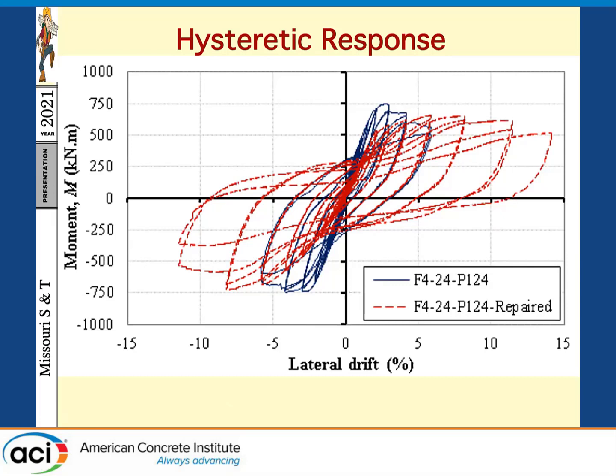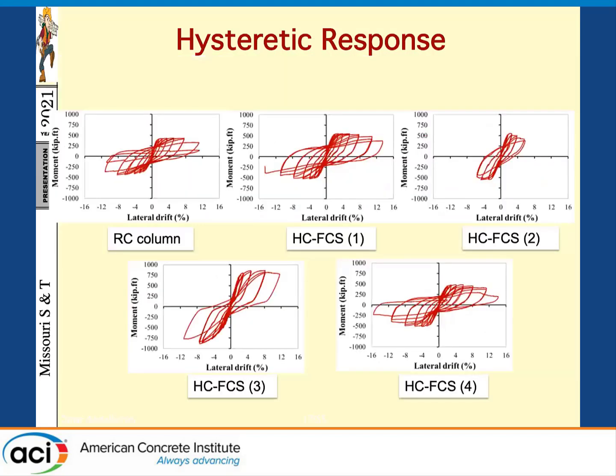One of the shortcomings of the repair was the initial stiffness. So the initial stiffness, if you look here for the blue one, is much higher compared to the red one. This was mainly due to the micro cracks that occurred in the concrete, and potentially any slip that happened on the steel during the first phase of testing before the repair.